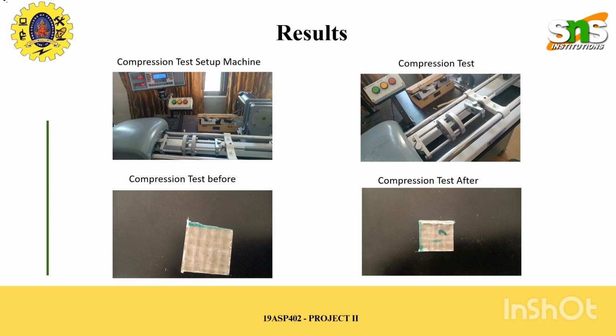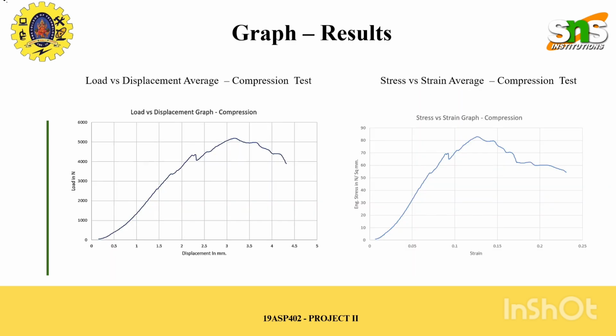In the compression test, the specimen is subjected to compressive loading until failure. The setup ensures that the load is applied uniformly across the surface. Observations before and after testing help in identifying deformation patterns and failure modes. This test is important for understanding how the material behaves under compressive forces.